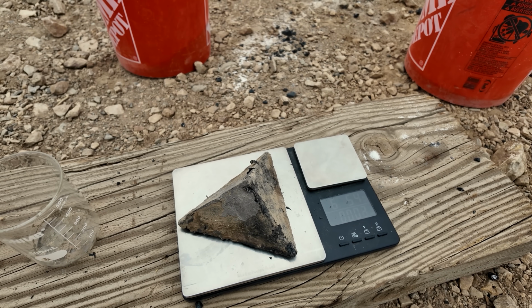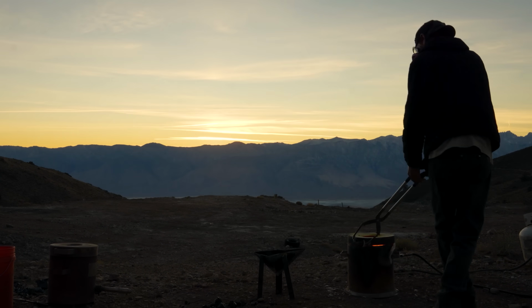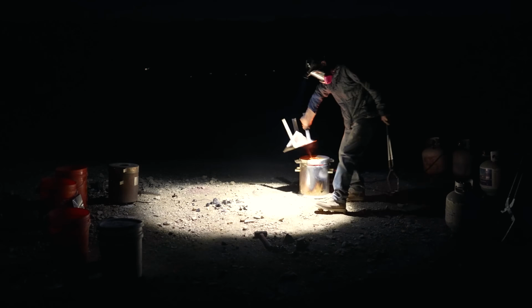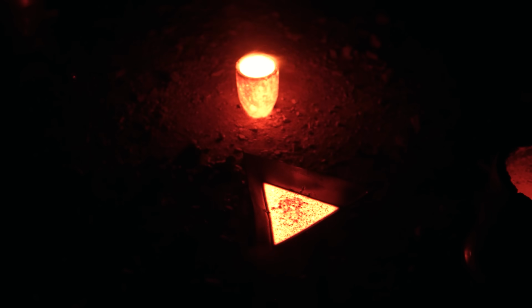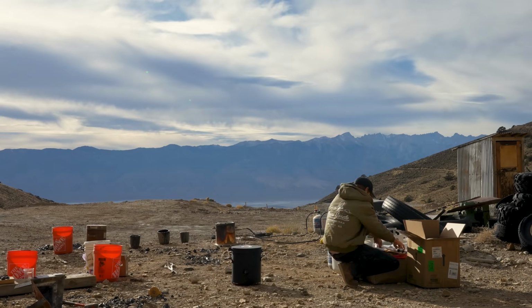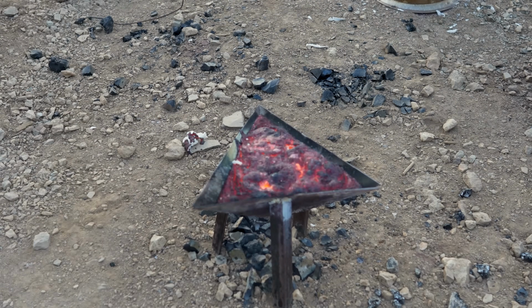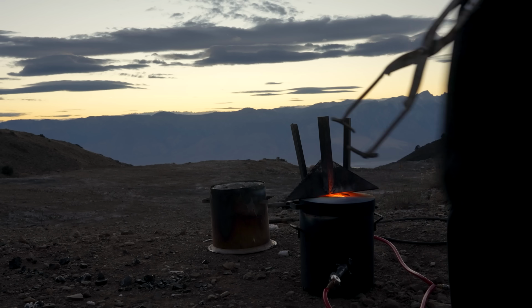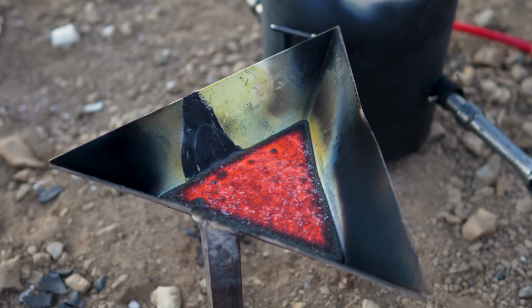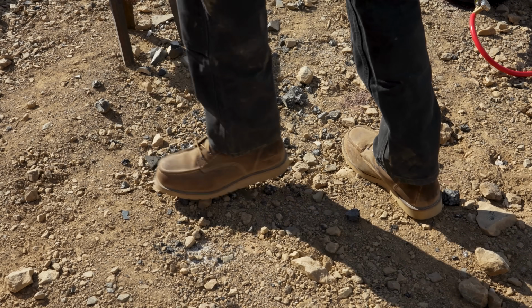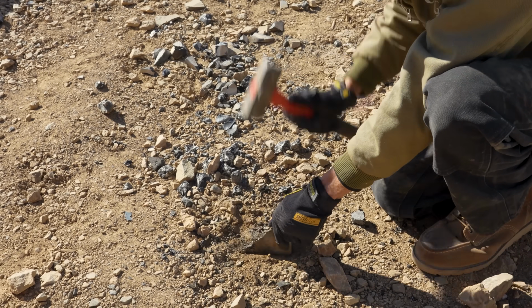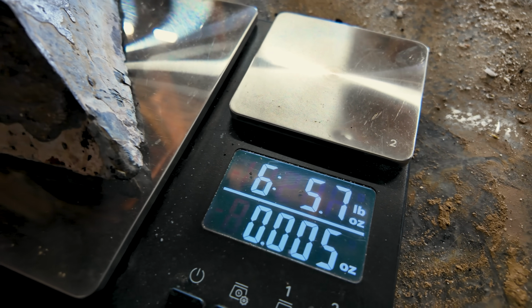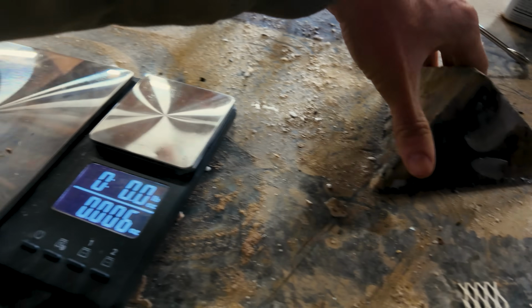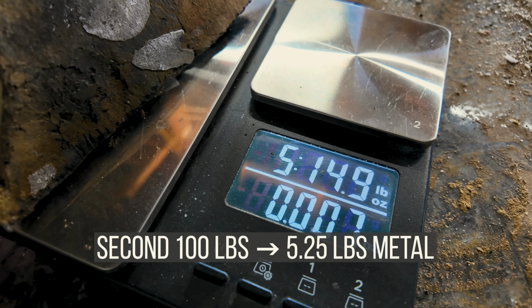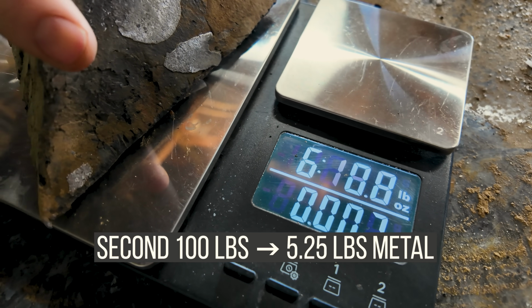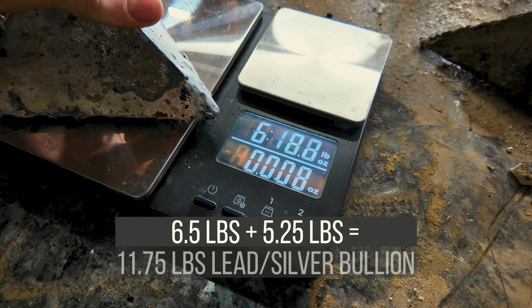So here's a very quick montage of even more smelting with 2 smelters. And double confirming our first at a weight of 6.5 pounds from the first 100 pounds of ore. And the second 100 pounds gave us about 5.25. So combined, 5.25, 6.5. And now comes the fun part.